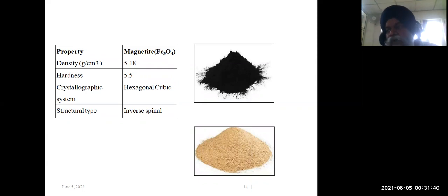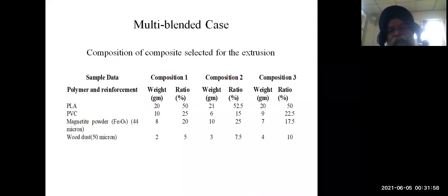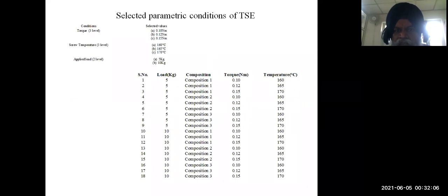Now how is it 4D? The 4D is basically this tile is getting an attractive effect because of the magnetic field as a stimulus. So we tried to find out what proportion we should use. So we selected different weight proportions of PLA, different weight proportions of PVC, different weight proportions of Fe3O4 and wood dust, and we did some DOE based upon design of experiment.